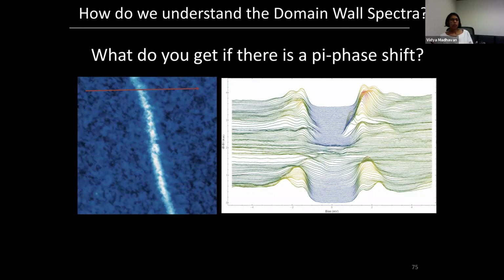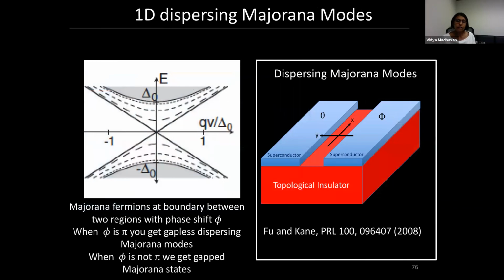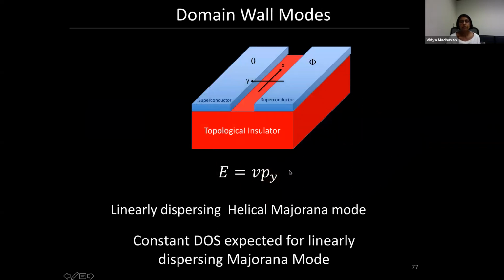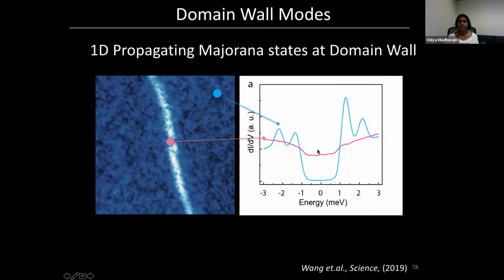So the question is, can this be a signature of Majorana fermions? And so the question is, what do you get if there's this pi phase shift? And the answer is that we know already from Fu and Kane's calculation that what you should see are linearly dispersing states in one dimension. And if you ask what is the density of states of anything that's dispersing linearly, it's flat, okay? So anything with linear dispersion in one dimension has a constant density of states. And that's exactly what we see. So all of these states are propagating Majorana fermions that live along these domain walls.